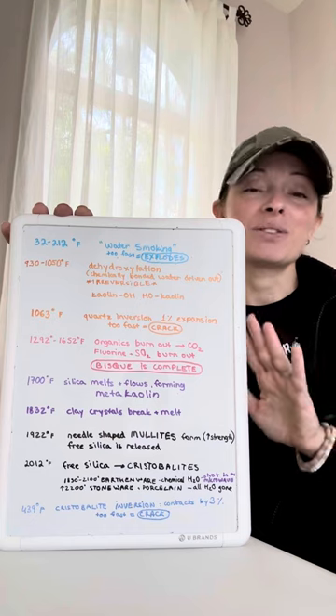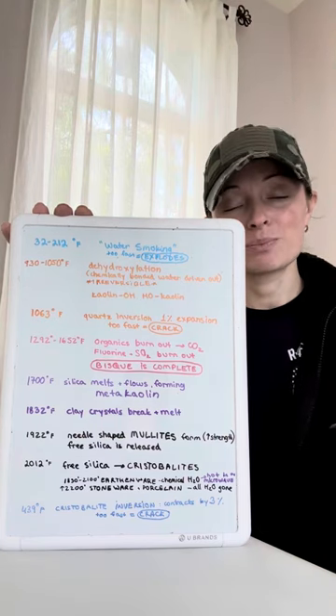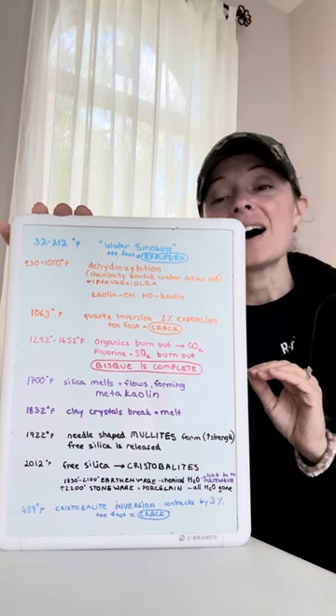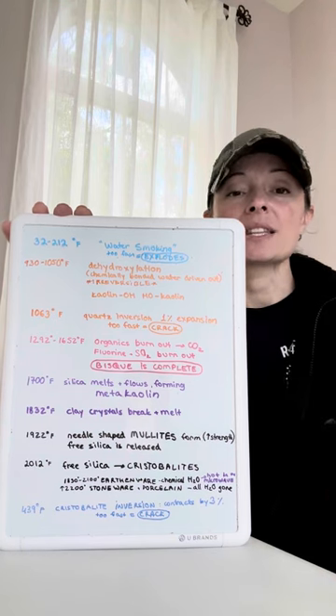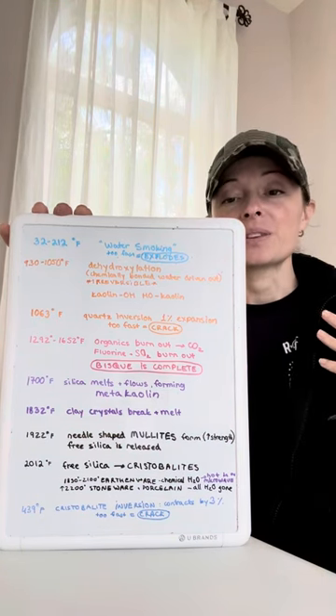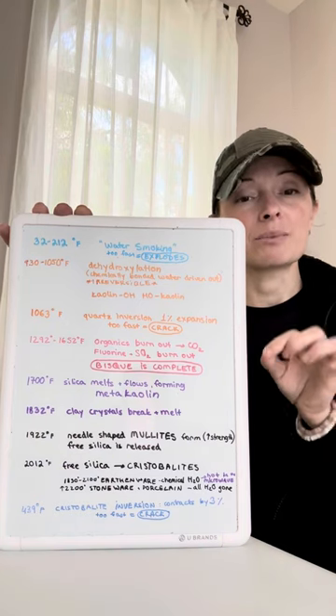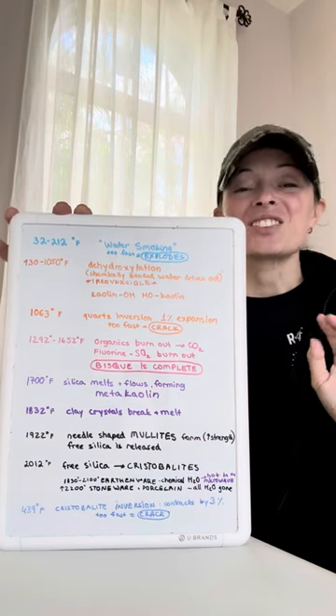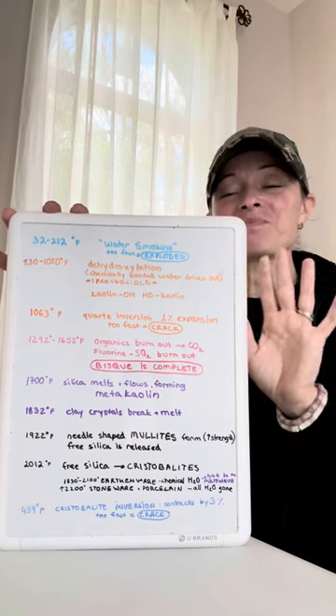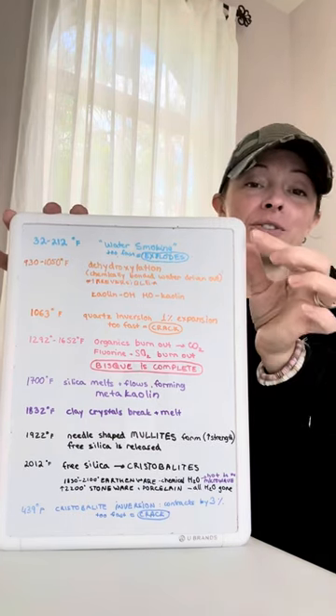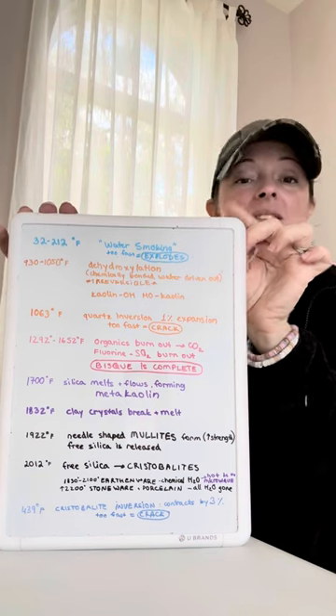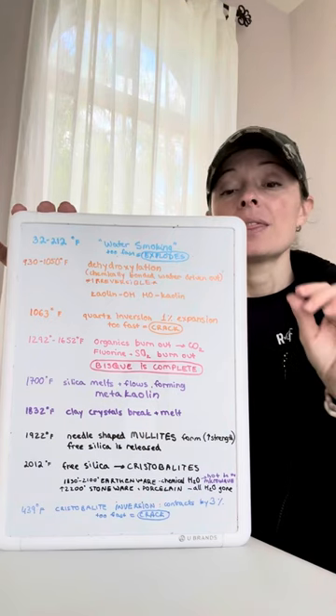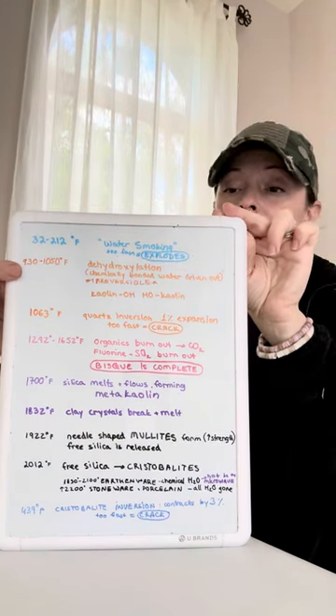Water smoking is just evaporation of water. There's nothing super special about it. There's not really any heat applied to your ware yet, not much of it anyway. You can achieve the same thing just by setting it out in the sun. However, if you don't get all of this water out of your piece before you start going higher in temperature, it will explode. So this goes back to my last video. Your water, when liquid becomes gas, it expands rapidly. And that is the first explosion you can have in a kiln.